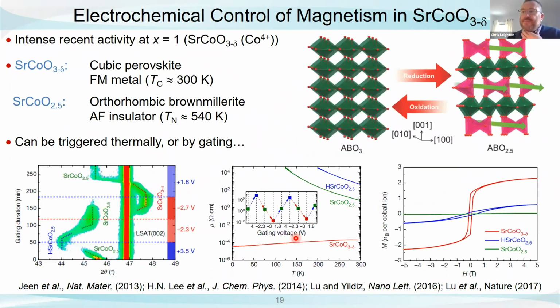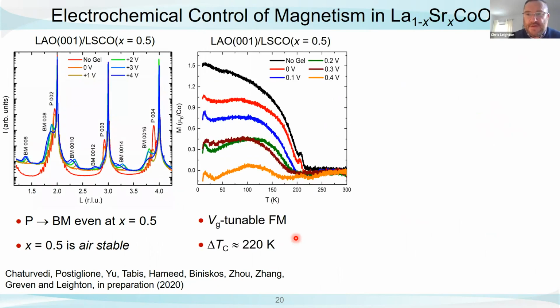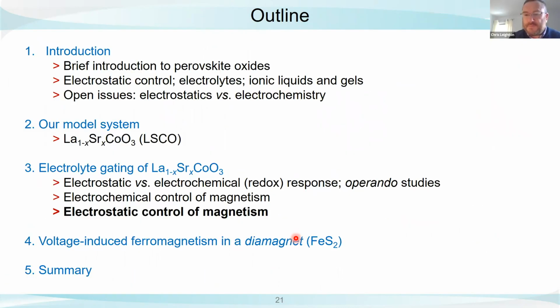Yeah, it's a good question. So the short answer is I'm not sure that anything will be better than a cobaltite in that respect. And the reason is this oxygen vacancy diffusivity, it is higher in cobalt-based perovskites than it is in many others. When we started this whole thing, we had, I think, a strong bias, just like everybody else, that probably the most important parameter was the enthalpy of formation of the oxygen vacancies. How easy is it to make an oxygen vacancy? We have completely reversed our ideas about that. We no longer think that that is the most important thing. We think actually the most important thing is the diffusivity.